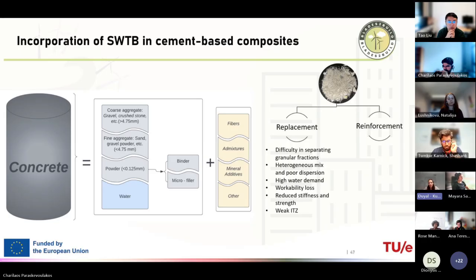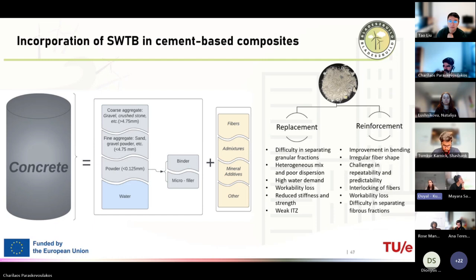And also inside of the concrete or mortar, if you replace at higher dosages, it usually ends with losing stiffness and strength, and it creates a lower and weaker interfacial zone. And also, of course, because of the cluster formation, as I mentioned, there is a workability loss. On the other hand, when we do the reinforcement, in most of the cases, we see some improvement in the bending properties. However, because the fibers are not uniform and different, even though you sort them, there is a challenge in repeatability of these results and predictability of these good results. And also, again, because of the interlocking, there is a workability loss. And again, it is really hard to sort a clean fiber fraction in this very heterogeneous waste stream.